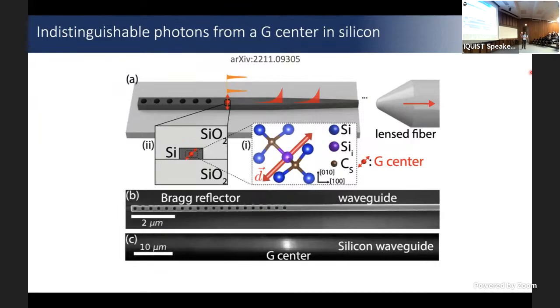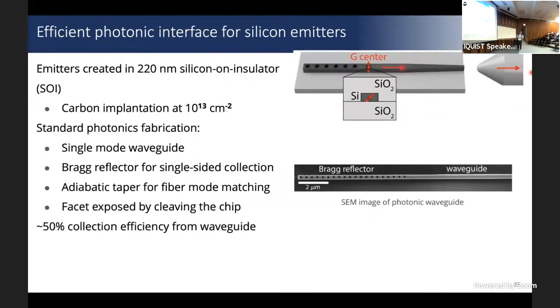And then we create emitters inside this waveguide via ion implantation and annealing. And then we design a mode converter such that this guided mode inside the silicon waveguide is coupled to the lensed fiber with high efficiency. Here are a little more details. We use standard silicon on insulator wafers. This is now a material we can buy, an 8-inch wafer. If you're a device researcher, it's nice to be working with wafers. So I like that. And then we take this wafer and do carbon ion implantation to create these defects.